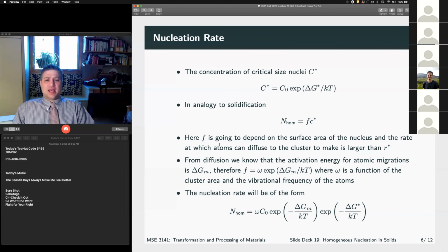F here is a little bit more complicated because it depends on the surface area of the nucleus and the rate at which the atoms can diffuse to the cluster, right, to make it larger than R star. So it's not a simple, straightforward number like it was in solidification, okay? What we know is that this is going to be dependent on diffusion. How fast can our atoms diffuse? So we're going to have a delta Gibbs free energy of migration here, right? So our attempt frequency also follows Boltzmann statistics, right? And so we have a nucleation rate term that combines everything together, right?